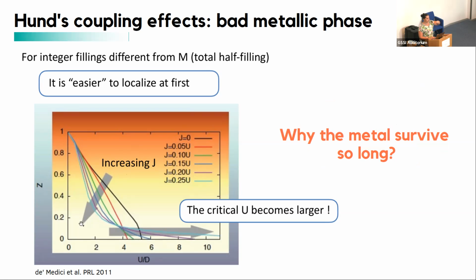One is that it is increasing localization at first, but then it is providing a very long range in the U parameter space of a bad metallic phase, in which Z is small but finite. So the critical U at which you have the transition to an insulator is very far. So why does the metal survive so long? Can we understand that? A way is that you can plot this Z curve in a 2D color map.